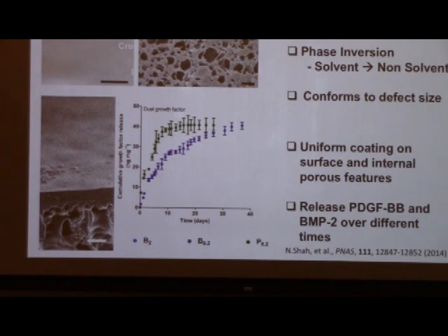It's a very thin film, but we can pack a large amount of growth factor into a tiny amount of space. Because of those rules of alternating charge, rather than having 1 or 2 weight percent as we would in the PLGA itself, in our case we have somewhere between 30 and 40% weight loading of our protein in the layer by layer film.